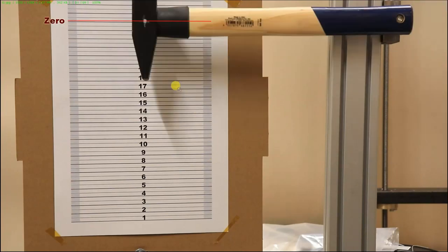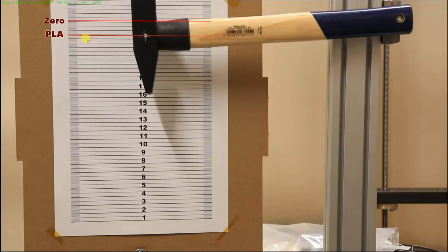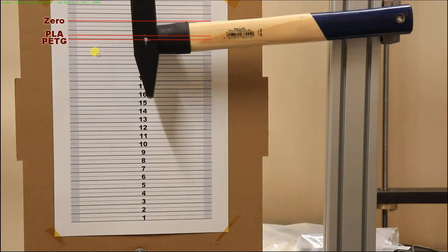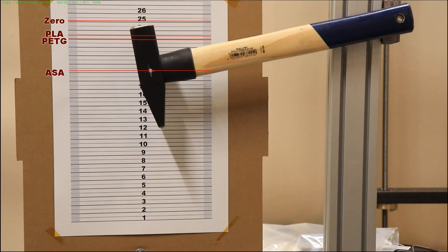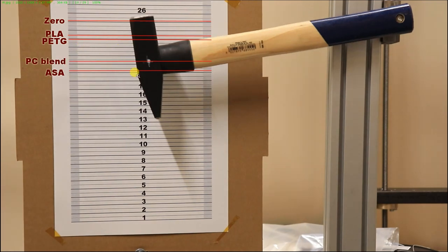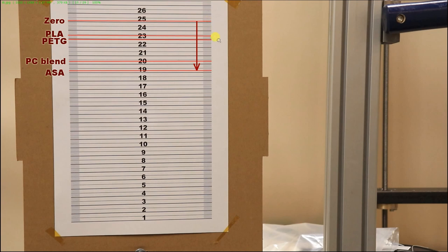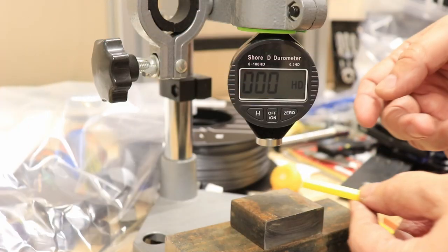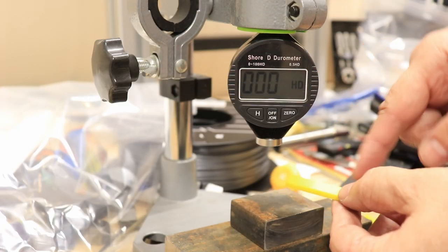So this is the scale, and this is the zero position. And this is after breaking the PLA test object. And this is the PETG, ASA, and PC blend. And if I measure everything from the zero position, I will get these values in millimeters. But in the calculation, I have to convert them to meters, multiply with g and the half kilogram hammer, and I will get the breaking energy in joules. And if I divide this by the cross-section area of the test object, I will get the unit as kilojoules per square meter. And now I want to measure the hardness with this Shore durometer, and I will measure perpendicular to the layers.